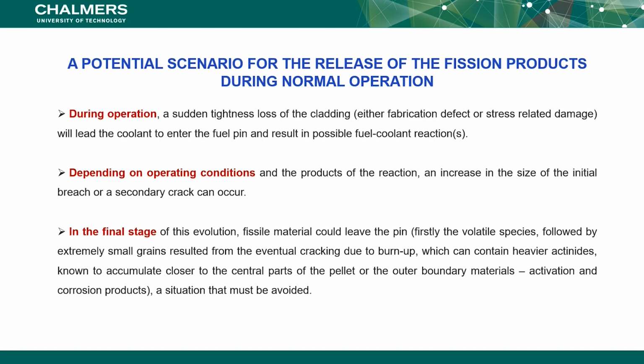So you have the volatile species going first, of course. They are going to be followed by extremely small grains, which are resulting from the cracking of the fuel because of the burnup. And this can also contain heavier actinides if the material comes from the center part of the fuel. And then basically you can have a release of the material into the coolant. Of course, this situation must be avoided at any price, but it is happening.